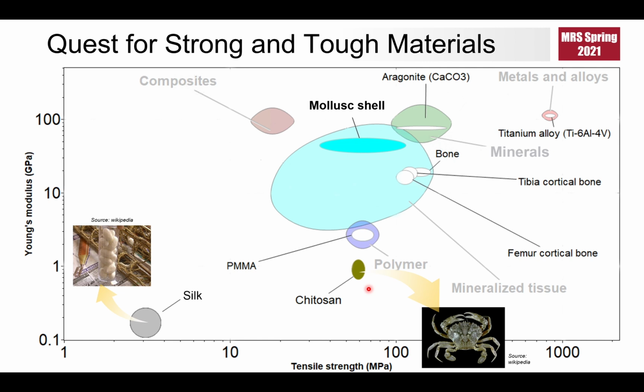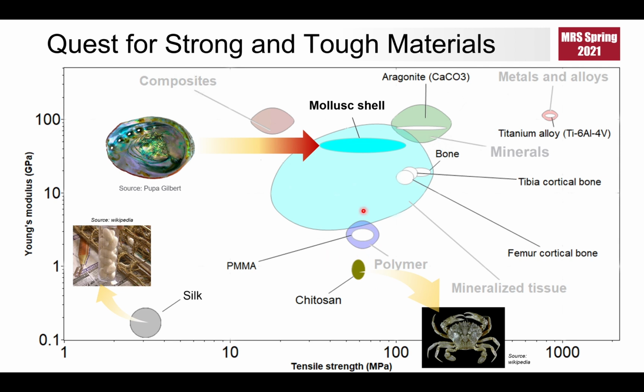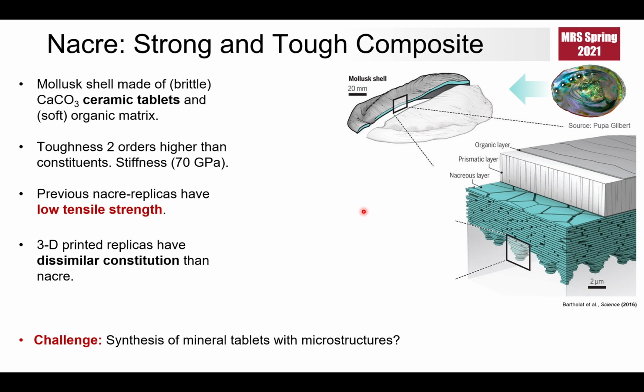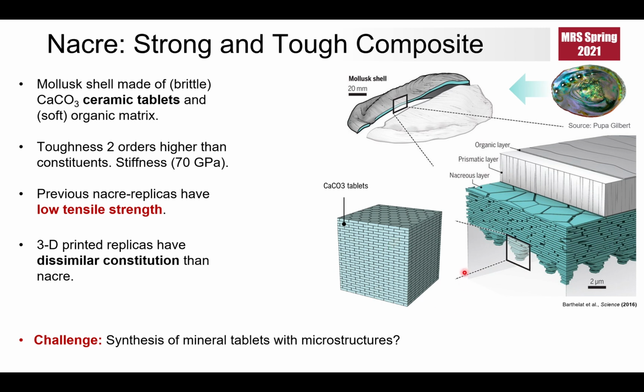Interestingly, one of the biological materials shown in this plot, the mollusk shell or nacre, is composed of a similar constituent, chitin, but has mechanical properties much higher than that of chitin. That's because nacre is actually a biocomposite of chitin and calcium carbonate mineral aragonite. Most importantly, the aragonite mineral in nacre is shaped like platelets and arranged like bricks in a cement wall. This brick mortar design has become the blueprint of a range of nacre mimetic composites developed so far.